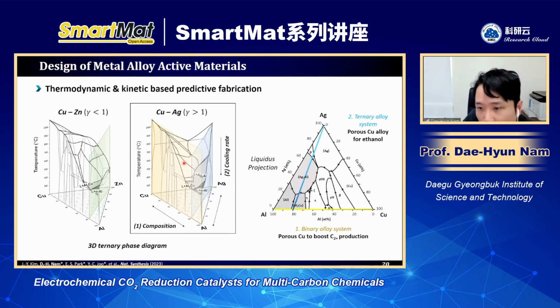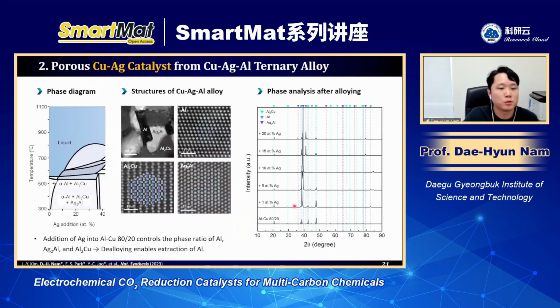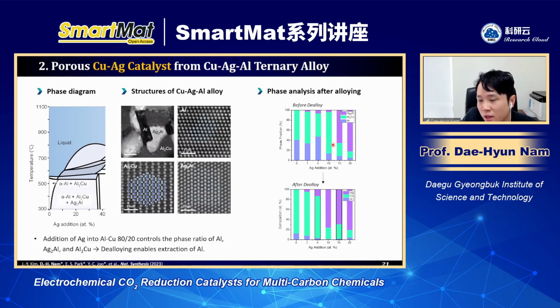After we confirmed the composition which can produce C2 chemicals the most, we started to put silver in it to control the selectivity between hydrocarbon and oxygenate. As we put silver in it, we can have three phases in the alloy process: aluminum silver, aluminum, and aluminum copper. It means that by controlling the silver content in the aluminum copper alloy, we can control the ratio between these three phases before dealloying. Then if we put this alloy into acid, this leaches the aluminum, and the remaining silver and copper can form different interfaces, because the original ratio between them has been controlled by the silver addition.